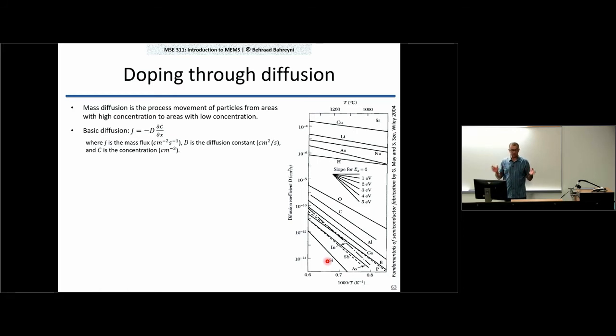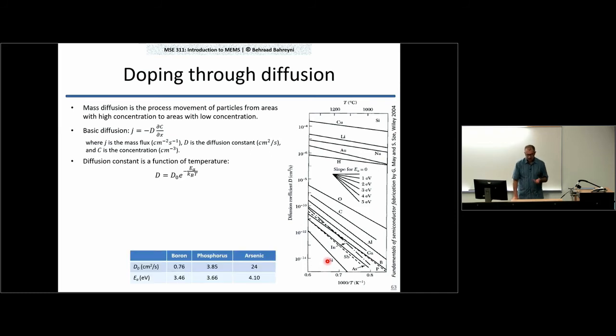And the problem is that at room temperature or low temperatures, the diffusion constant is really small, but that's a temperature dependent coefficient. We raise the temperature and everything becomes easier. The diffusion becomes easier. On the right graph, you see how the diffusion constant changes with temperature. So the axis, if you look at the bottom axis, it's 1000 over T in Kelvin. At the top, you have it in Celsius. You can see that as we raise the temperature, the diffusion constant exponentially increases. You can actually find the diffusion constant from that equation, and the numbers for boron, phosphorus, and arsenic, that are your typical dopants, are mentioned in the table below.